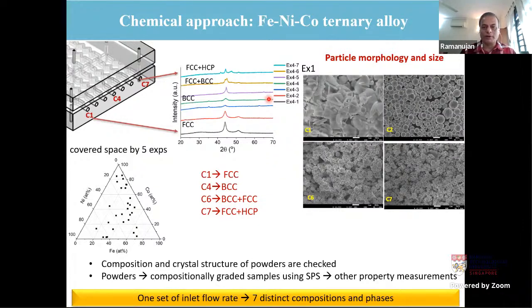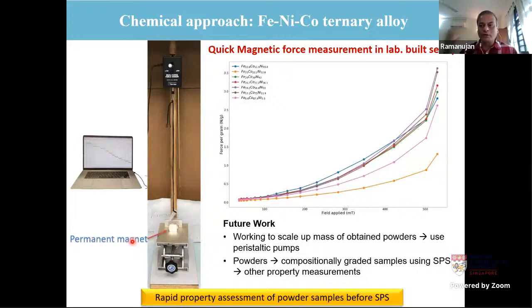So then we produce these powders. You can see these powders which have been produced using this method, and we can examine their crystal structure. And you can see that we can see a variation in the crystal structure from one output channel to another, from FCC, BCC, FCC plus BCC, and FCC plus HCP. So in a relatively short time, we can scan several compositions in this iron, cobalt, nickel ternary space. So this is just for the powders. But then we can also go further, and we want to quickly know whether something is magnetic or not, because we are now screening. So we have set up our own home-built quick magnetic force measurement system.